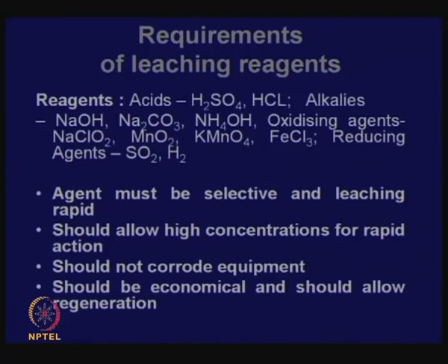What are the reagents that we use? Reagents can be acids, like H2SO4, HCl. You know that H2SO4 is a stronger medium for leaching, but sometimes HCl may be preferred. There are alkalis: sodium hydroxide, sodium carbonate, ammonium hydroxide. Oxidizing agents are necessary sometimes, like NaClO2 or MnO2, KMnO4, FeCl3, which will oxidize some species in the aqueous media. Sometimes we need reducing agents, SO2 and H2, to reduce certain species in the aqueous media.